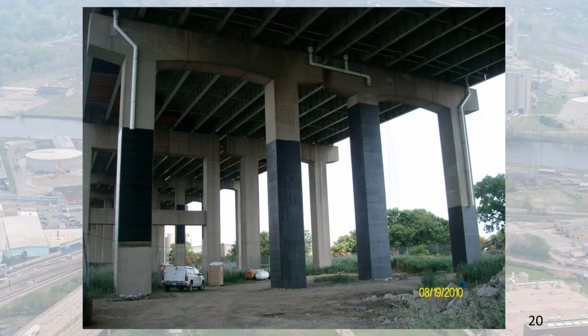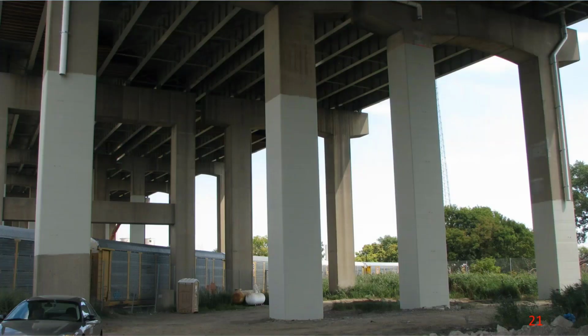And so after the FRP is installed, typically you put another layer on the top of the FRP of the epoxy to further coat and make sure that the fibers are coated and bonded with the epoxy system. And then after that curing takes place, you top coat it for environmental protection and against UV protection, although the epoxy itself also has chemicals to resist UV degradation. The top coat is generally gray concrete color, and depending on the particular manufacturer, they'll have specific requirements. They'll have either their own brand, or they'll have a list of compatible products you can use for top coat for both aesthetics and for environmental protection.